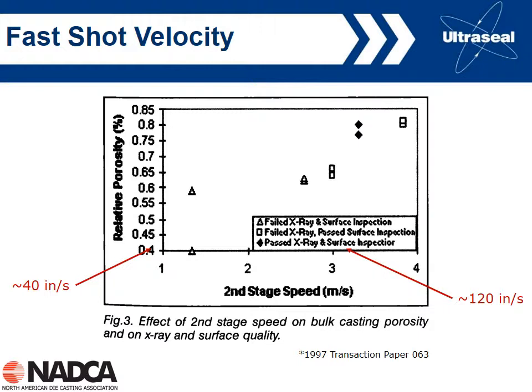And it's these large pores that cause us to fail X-ray. As we go faster, we get to the area with the black diamonds. This seems to be a bit of a sweet spot. Here we've passed both X-ray and surface inspection. Although the overall porosity was higher, we seem to be getting a better distribution of porosity, a smaller porosity that allows us to pass X-ray.